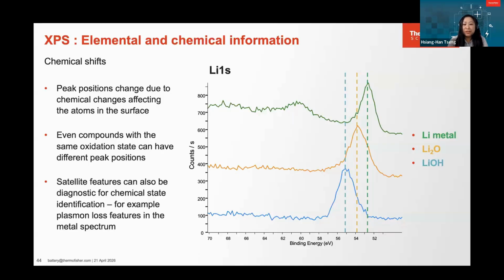That's pretty good with what you can do with XPS, but there's one thing we should remember. In XPS, we only have one peak for lithium. So if you expect a peak coming from another element that potentially overlaps, then in treating the data you will have to do peak deconvolution carefully so that you can actually resolve the lithium chemistry.